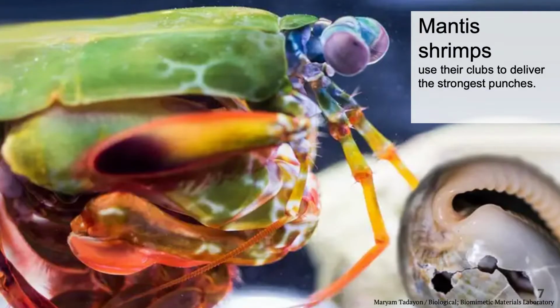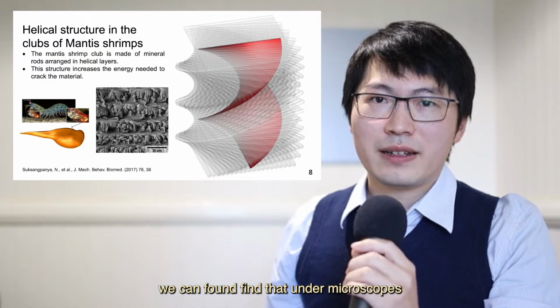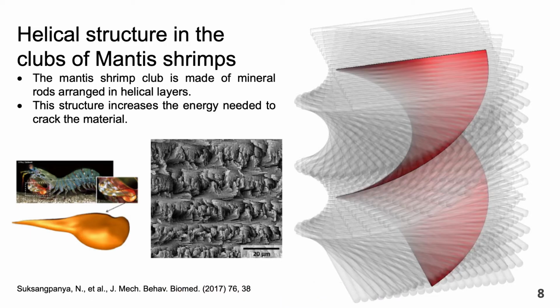If we take a closer look at the clubs of the mantis shrimps, which are used to hit its prey, we found that under a microscope, there is a helical structure in these materials. Such structure is similar to the layered structure in nacre, but instead of using tablets, it uses layers of mineral rod arranged in a spiral shape.